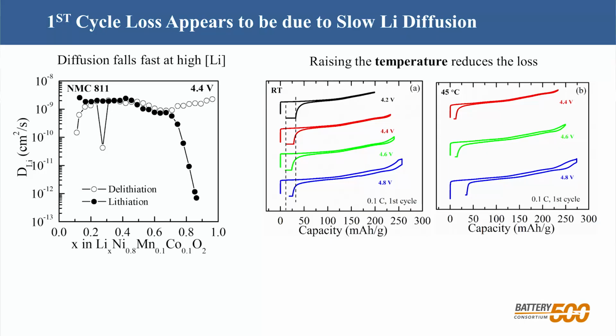It's the same with these lithium cells. And taking the lithium out, there's no such problem. Those are the open circles. So it can all flow out without any issues. So you can do fast charging with these materials, but not necessarily fast discharging all the way.